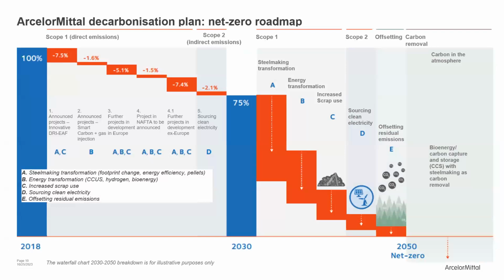Here on this slide, you can see the ArcelorMittal decarbonization plan towards a net zero situation. This is our roadmap for the whole group, so worldwide. You can see that this roadmap is based on 5 main pillars. The first one is steelmaking transformation. What is behind this word? We will slowly transition from our blast furnace, basic oxygen furnace sites towards DRI plus EAF, so we will really make significant industrial changes on our production sites. Then the second pillar, energy transformation, where we will be leveraging cleaner energy. One example is the Steelanol initiative at our site in Ghent, where we use the blast furnace gases that are transformed into bioethanol, which is used, for example, in the transport industry. These kinds of initiatives are gathered under this pillar, energy transformation.